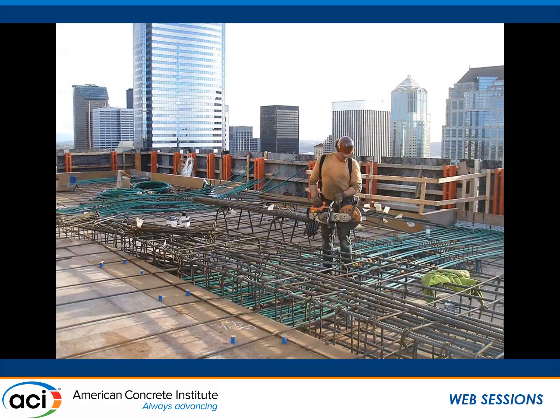The modulus on this building was not an issue because we had a core whose span to depth is about 12, at a 38 by 38 foot core. So the stiffness was not as critical. Ductility was important because of seismic forces. But more importantly, compressive strength was so important for the columns.